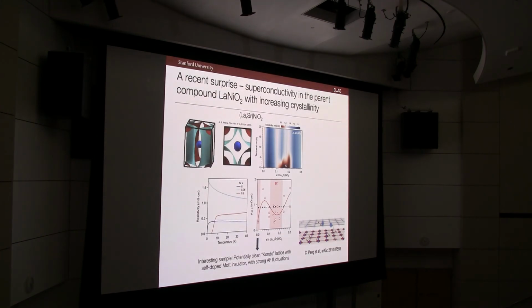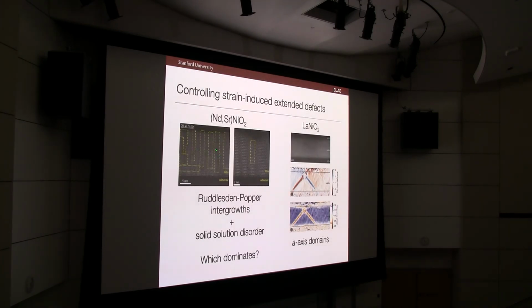Now, let me go back a little bit and tell you about what cleaner means and where we are on that problem. I had shown you that in the early days of the originally studied neodymium type of nickelates, we were able to make, and we were quite proud, this was quite hard work, nominally single crystal thin films, but there was quite a high density of extended defects. Without going into the details, these were often antiphase boundary shifts or so-called Ruddlesden-Popper intergrowths. We got better and better at eliminating them, but they're still there to fairly high density. So our question, which we don't know the answer to, is to what degree is scattering dominated by these extended defects or that associated with the solid solution disorder?